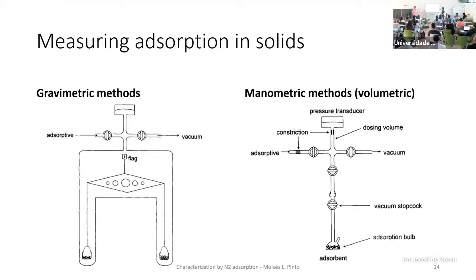Another way is the manometric method, also called the volumetric method. In this case, you have a dosing volume like this. You need to calibrate this volume very well first, and then we put here a certain pressure, and we open and give this dose to the adsorbent. The pressure will decrease because you will have adsorption here, and then you can use an equation of state to relate the pressure difference with the amount adsorbed. Then you close again, give a second dose, and so on. The automatic equipment that you most probably have to determine nitrogen adsorption isotherms is of this type.